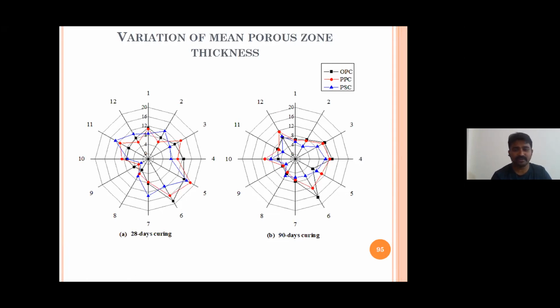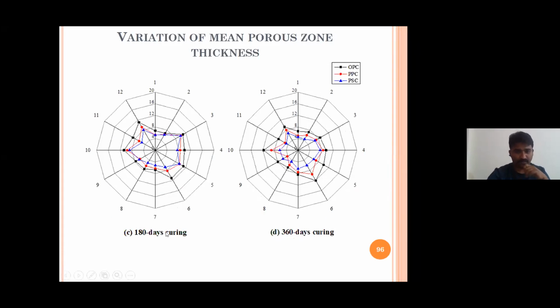This is one important or major finding that we can draw from our research. As the curing period is increasing, the porous zone thickness is reducing. This is for 180 days, still it is reducing. Even at 360 days, it is reducing. See, the reduction in porous zone thickness for PSC is higher compared to OPC concrete, right? So this is for 28 days, 90 days, 180 days and 360 days. For all of them, the porous zone thickness is reducing, but the reduction rate of PSC concrete is slightly higher than OPC concrete.